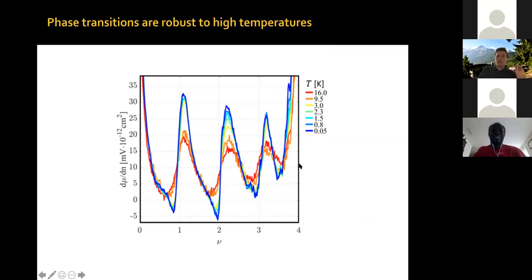So the first thing that I want to say is that this behavior, which as I'm going to tell you in a moment is due to phase transitions, is something that occurs at energy scales well above any superconducting or correlated insulator temperature scale, okay? The superconducting TC for these devices is a maximum of 3 Kelvin. Correlated insulator behavior typically is there up to a few Kelvins, maybe 4 or 5 Kelvin, sometimes 10 Kelvin. This is happening at 16 Kelvin, and in fact, by now we have extra data that this is happening at 30, 40, even 50 Kelvin. Okay, so this is a behavior that happens above any other type of low energy physics that you can measure at lower temperatures. Can I ask a question?